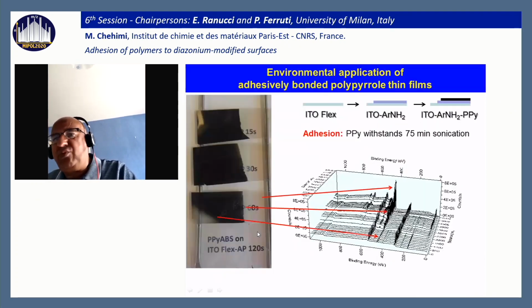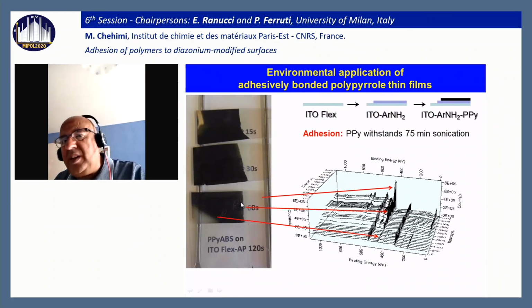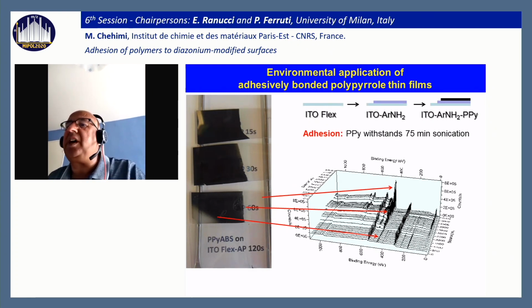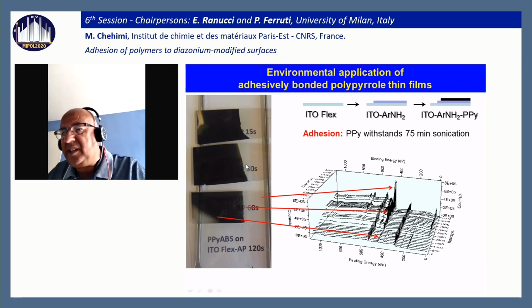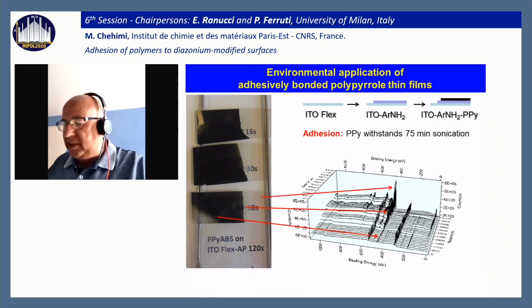So if the aryl layer is very thick, the electrode becomes passivated and insulated, and there is no more electropolymerization. So we have tuned the time for grafting the aryl group from the diazonium salts. You can see here for 15 seconds or 30 seconds, we can have the polymer fabricated by electrochemistry. But if the aryl layer is very thick, this is not possible because the electrode becomes insulating.